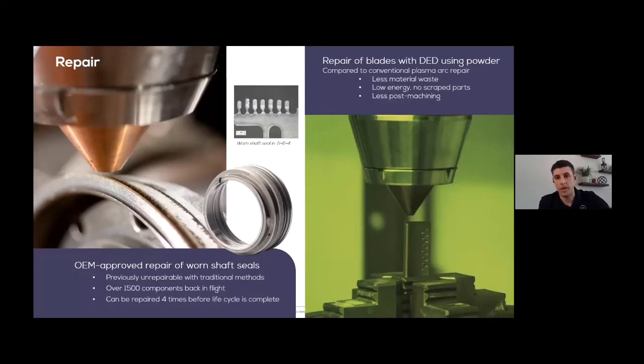Repair is a great application. In this example, we're showing a shaft seal. It has knife seals at the end of it, and these tend to wear out over time. This part's made out of titanium, so it's a very expensive part to machine from scratch. We can go back in and add these worn knife seals back onto the part, and then there's just a small machining operation to get them back into tolerance. So rather than scrapping this part, you can repair it up to 4 times before it has to be scrapped, extending the life of the part pretty significantly.